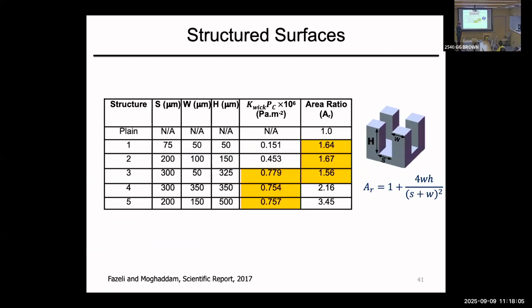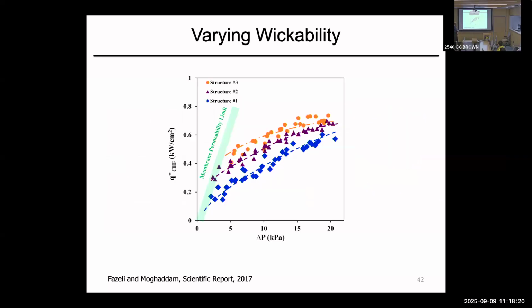We do a planar surface, number one. Then we do a test where we keep the surface area constant and increase the capillary wicking, and then we keep the capillary constant and increase the surface area. This is the limit of the membrane that you cannot go beyond, because this pressure has a certain limit. If you go through different surfaces, the one that has the highest capillary wickability is substantially higher. But once you start putting pressure on and squeeze the bubbles and liquid, squeeze the bubbles out and the liquid in, the effect of difference due to wickability goes away, and they come to the same number.